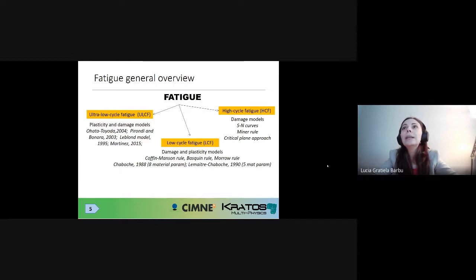And generally what you will find in this area is a preponderance of damage models, the majority of damage models are based on the S-N curve, on the Wöhler curves. And in the case where we have a combination of cyclic loading, you will find that most people and most software also use the Miner rule, which is a linear damage accumulation rule, summing up the damage due to each different type of cyclic loading. Also, there is another family of models which has been proposed in the last years, I would say starting from 2014, 2015, which is the critical plane approach, which has its own particularities. It's interesting for you to check it out if you're curious about this. However, this is not the approach that we're using at CIMNE.